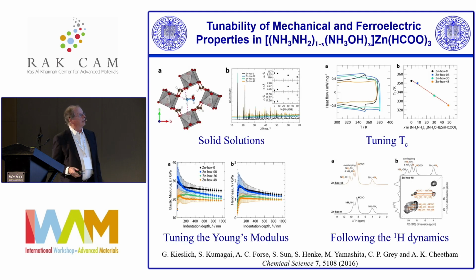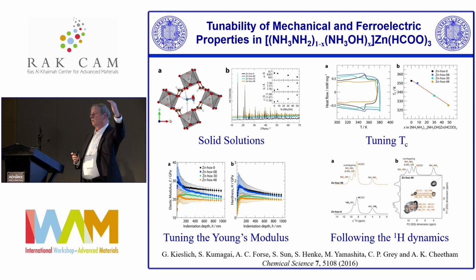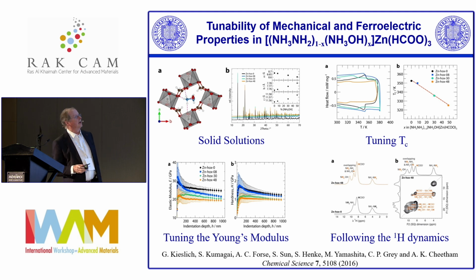But we also showed that if you take that hydrazinium with its very high phase transition, you can actually control the temperature of the ferroelectric phase transition by replacing some of the hydrazinium with, in this case, hydroxyl ammonium, which has less hydrogen bonding. And so it weakens the hydrogen bond interactions that lead to the ordering. And so these things only order at lower temperatures. So you get pretty much a linear relationship between the degree of substitution of the hydrazinium and the Curie temperature of the ferroelectricity. We did lots of other things, NMR and so on, which I don't have time to talk about.